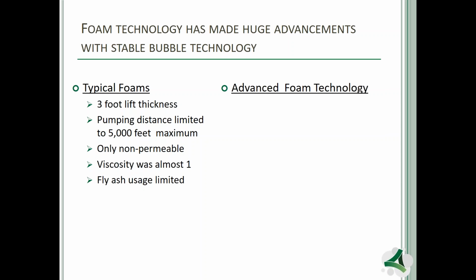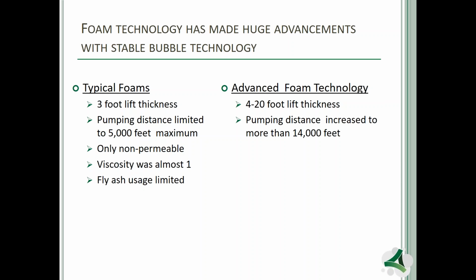If we take a look at what we are doing today with the cellular concrete and with the bubble structures, we are now doing lifts in the tune of 4 to 20 feet in height. We actually just had an installer in Texas do a void fill scenario in the shape of a funnel that was 2 feet diameter at the bottom, flaring up to 25 feet at the top, and was a total of a 35-foot height void at a bridge abutment, which they filled up in one lift. And when it came back the next morning, there was less than a half inch drop in the overall material. So we're getting tremendous lift heights with the bubble structure and not losing the bubble structure.